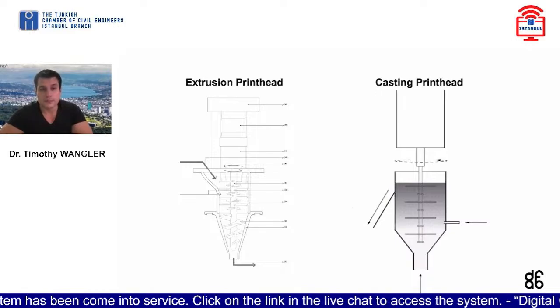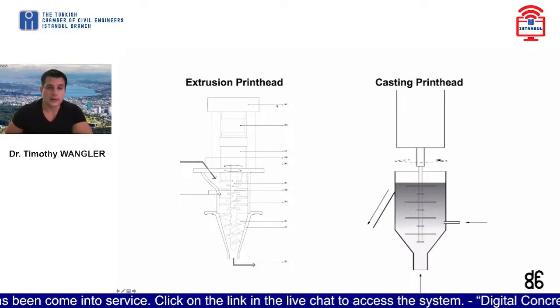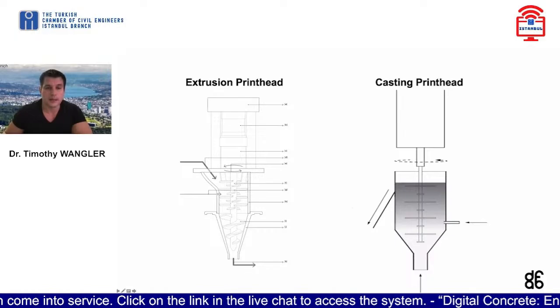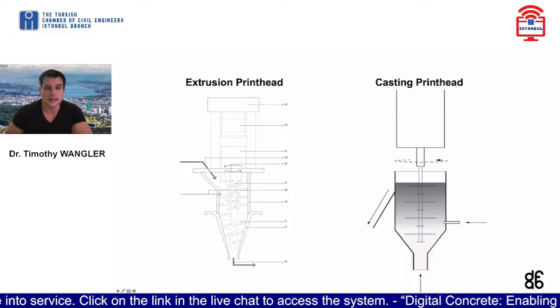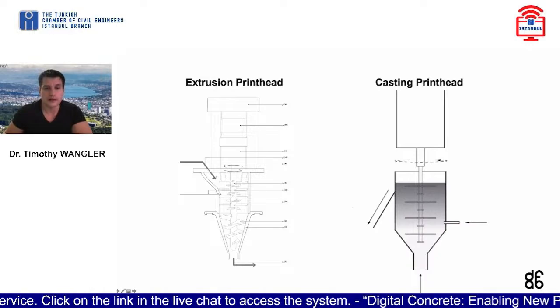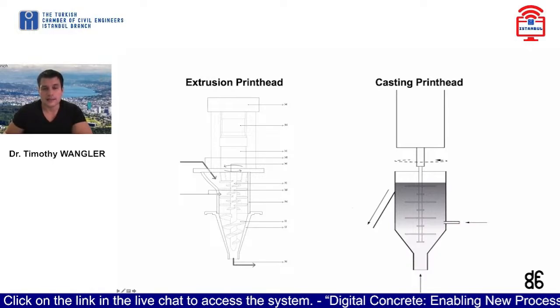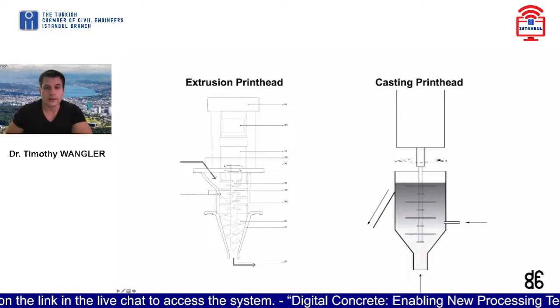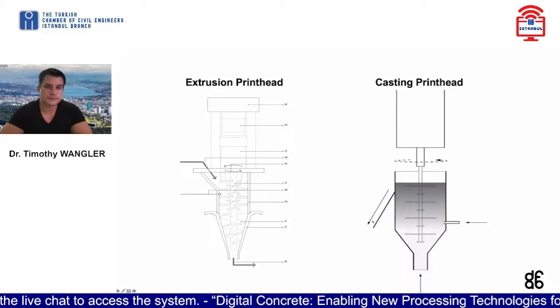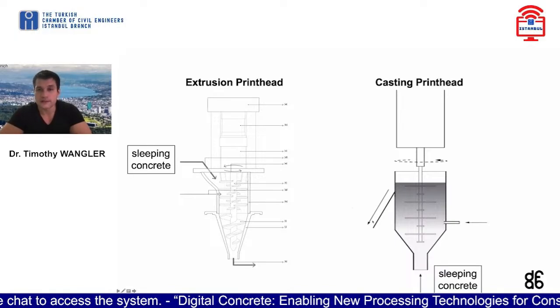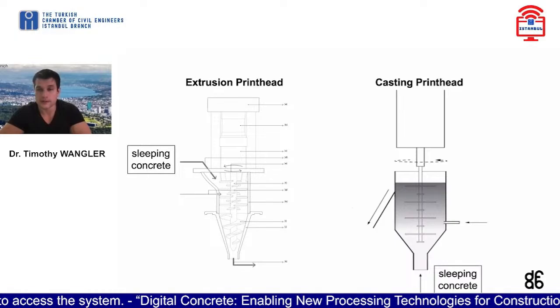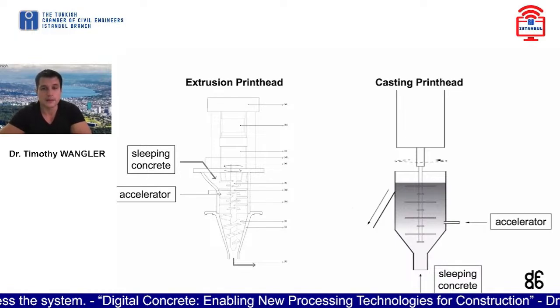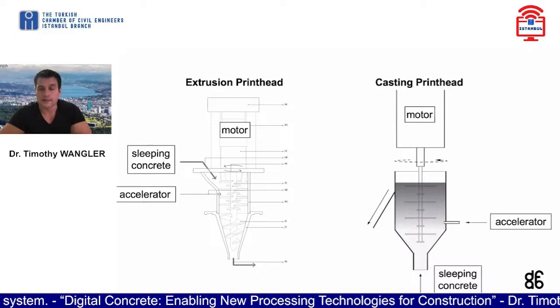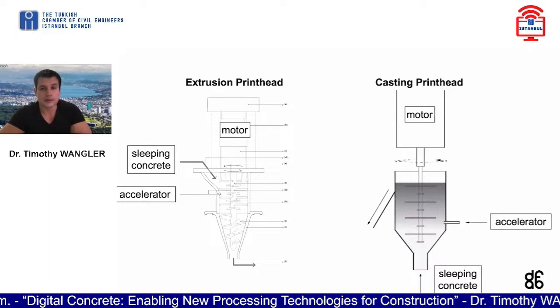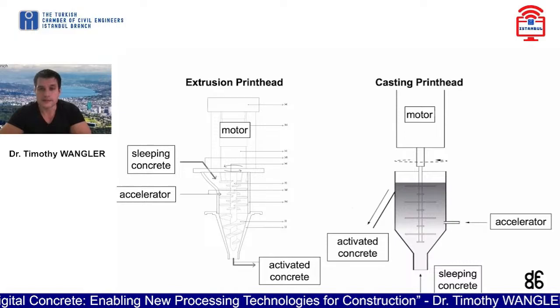We have developed a couple of printheads. On the left, you see our extrusion printhead, where we have some impellers that are mixing in the accelerator that we inject here before it comes out of the extruder. And here's our casting printhead, where we inject an accelerator before it comes out of a chute into the formwork. So there's some kind of sleeping concrete. We generally retard our concrete to get a longer open time. Add the accelerator, have an active mixing unit with a motor before out comes the activated concrete.